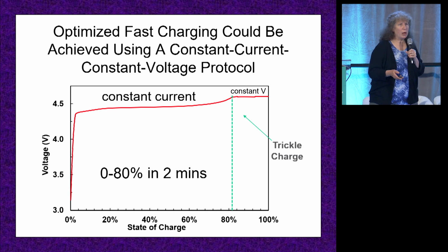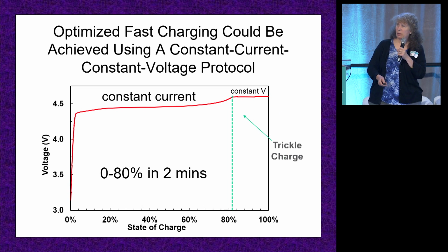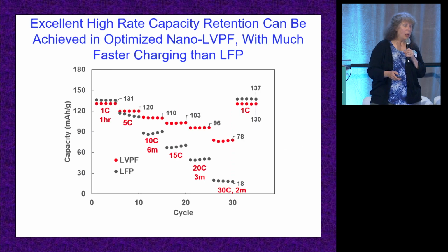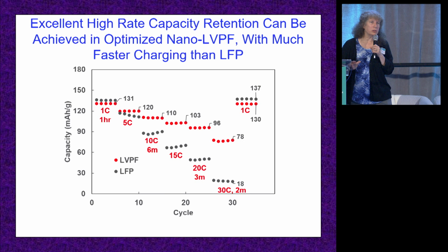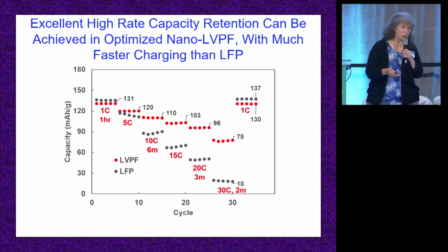So in the fastest charging protocols, we use what's called a constant current, constant voltage protocol, where we charge rapidly up to about 80% of the state of charge in 2 minutes, and then we trickle charge the rest of the capacity. That gives you the most capacity. And this is just an overall summary of what we've been able to accomplish.